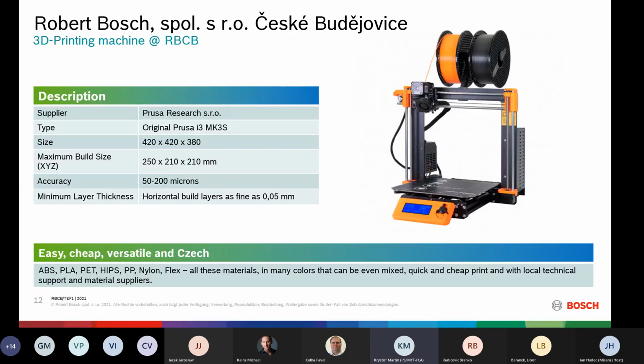The next technology is FDM. We use in our department and in our plant many small, very famous Czech printers from the firm Prusa, in very different modifications, as a single printer or as a multi-material, or I mean multicolor, printer. The maximum build size is 250 times 210 times 210 millimeters, and accuracy is between 50 and 200 microns. The minimum build layer is 0.05 millimeter, but usually we print with 0.15 millimeters.